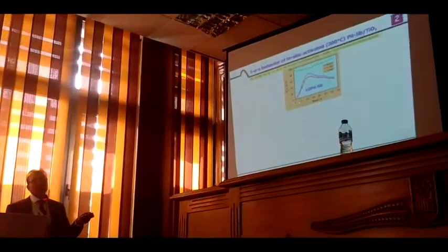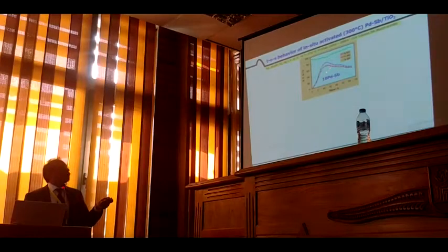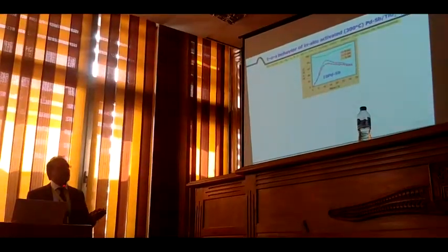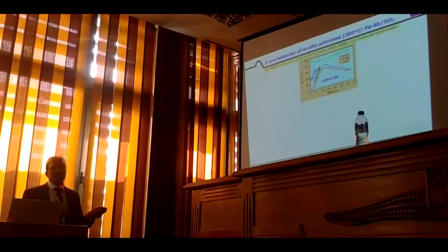The catalyst exhibited very low initial activity, nearly zero, starting from zero, and then increasing continuously until 10 or 11 hours, remains stable for 2 to 3 hours, not much, and then going down. It undergoes deactivation. What is the reason for this increase in conversion, and what is the reason for this deactivation? The reason for the increase in yield is the increase in palladium particle size. You may wonder, how come this? I will try to convince you in a moment. And the deactivation is due to coke.